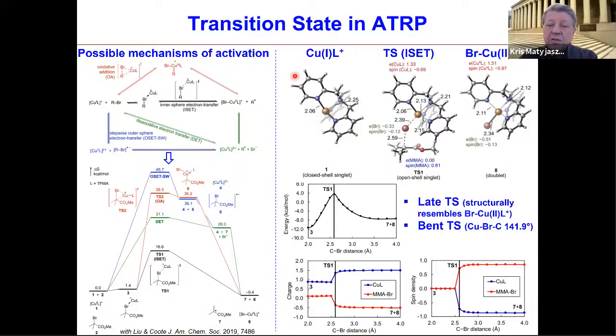In some sense, we start with this copper(I) species. It is a 3d10 configuration, so it is a closed shell singlet. And then the product is a doublet with 3d9 configuration, but you pass through a transition state. This transition state is very unusual. It is not straight, not 180 degrees, but the carbon-halogen-copper bond is bent, around 140 degrees. This is due to some attractive interactions between substituents and ligands on copper. The transition state is rather late, which means it resembles the products. You can see that in the transition state, where you have the highest energy, the charge is practically already developed like in the product. The same situation holds for the spin. So the transition state is rather late under these conditions.